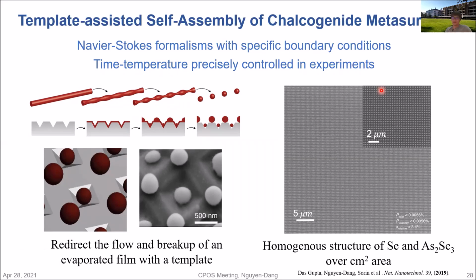During my PhD, I carried out a project using templated substrates to fabricate metasurfaces of chalcogenide glasses. The math I would not mention here due to the lack of time. Basically, we solved the Navier-Stokes equations with very specific boundary conditions, a patterned boundary, and we control the time and temperature relationship in order to make the wetting or the breakup happen at the precise positions that we chose.